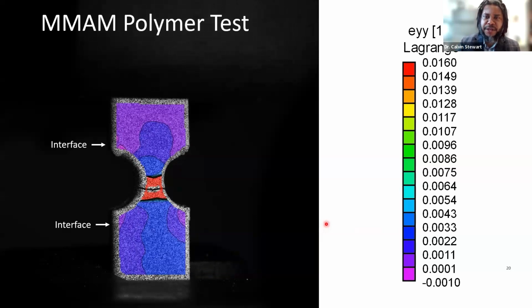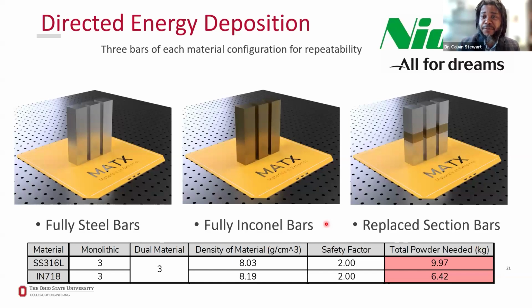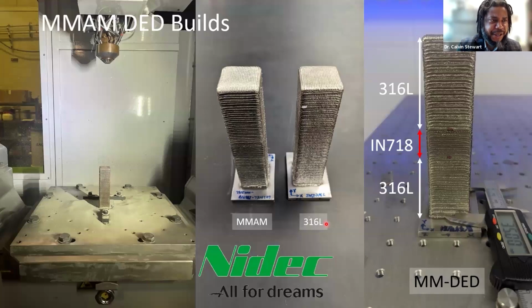Really cool stuff. So now we've moved from the polymer-based science to that multi-metal-based AM. We're working with this company, Nidec, doing directed energy deposition, blown powder, multi-metal additive manufacturing. And at the current point, we've created some bars that are a combination of 316, our weaker material, with Inconel 718, our nickel-based super alloy. And at this point, all we got to do is cut them and repeat our test methods to prove out this new design for multi-metal additive manufacturing approach.